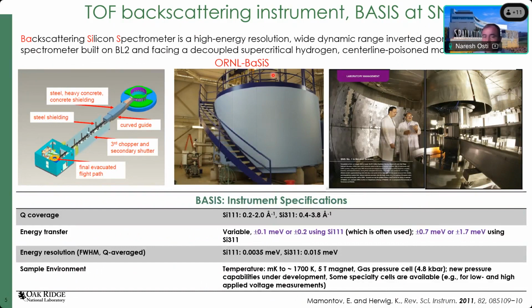You can see this is a big tank, and this big tank is the end of the 84-meter-long neutron flight path. With the combination of three different chopper systems and the analyzer panel that you can see inside the instrument, we can have a very wide Q range, from 0.2 inverse angstrom all the way to 4 inverse angstrom. The combination also gives you a wide dynamic range, so that you can probe the dynamics that happen from the 1 nanosecond to 1 picosecond time scale.